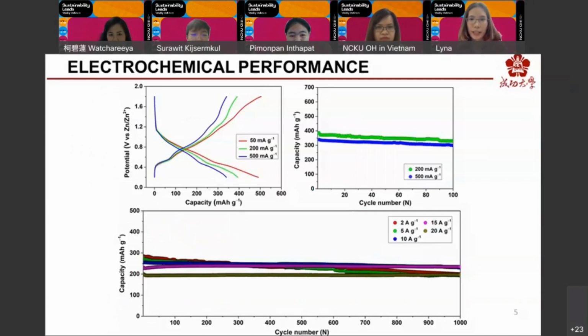HATAQ exhibits high capacity as well as stable capacity retention. As you can see, the capacity of around 500 milliamps per gram was obtained at the current density of 50 milliamps per gram, which is very close to the theoretical capacity of HATAQ. And the current density was also increased to 20 amps per gram with a stable retention for 1,000 cycles.